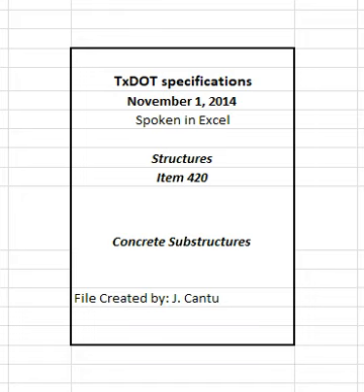Dampen formed surfaces and surfaces that have been given a first rub so they are moist at the time of application of the membrane. Leave the film unbroken for the minimum curing period specified when membrane is used for complete curing. Correct damaged membrane immediately by reapplication of membrane. Polyethylene sheeting, burlap polyethylene mats, or laminated mats in close contact with the concrete surfaces are equivalent to membrane curing. 4.11 Removal of forms and falsework.